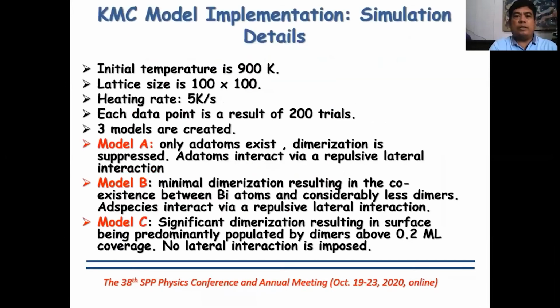Model and implementation. Simulation details. Initial temperature is 900 K, lattice size is 100 by 100, heating rate is 5 Kelvin per second. Each data point is a result of 200 trials. Three models are created. Model A: only adatoms exist, dimerization is suppressed. Adatoms interact via repulsive lateral interaction.